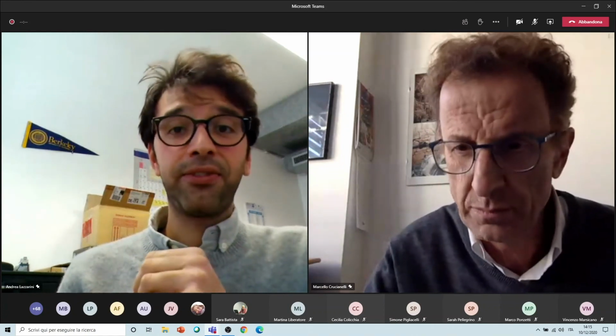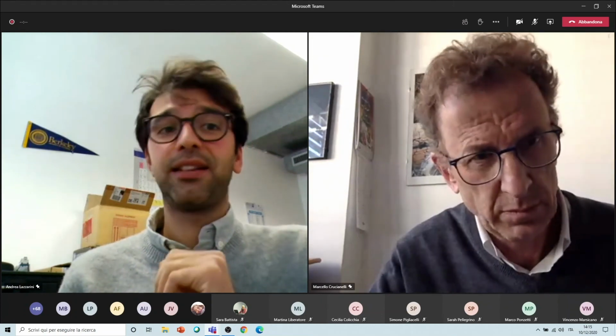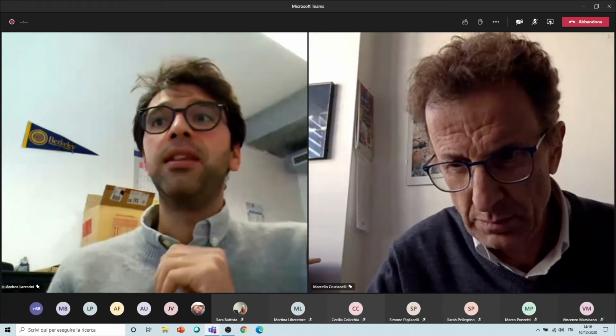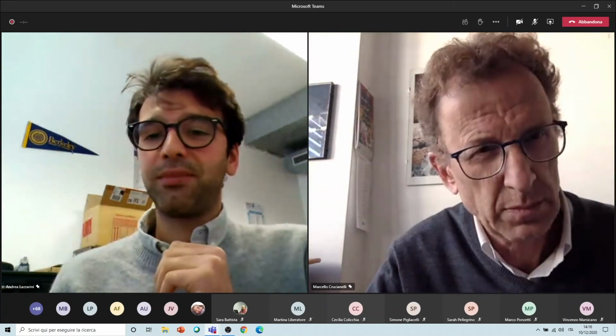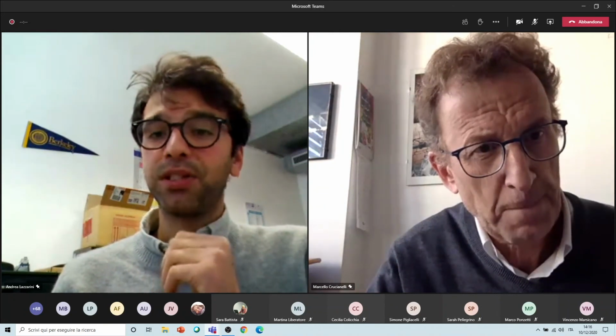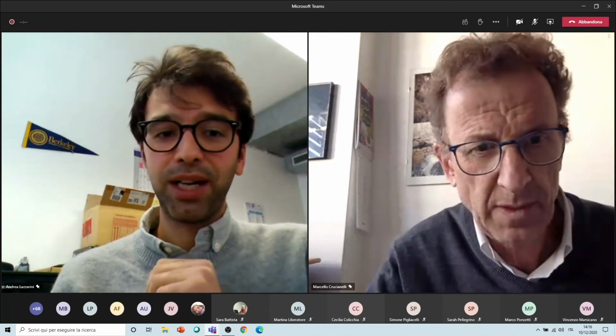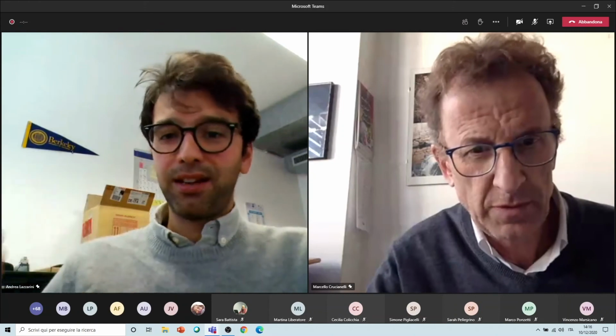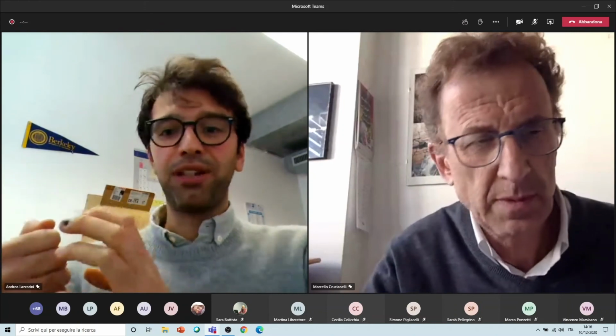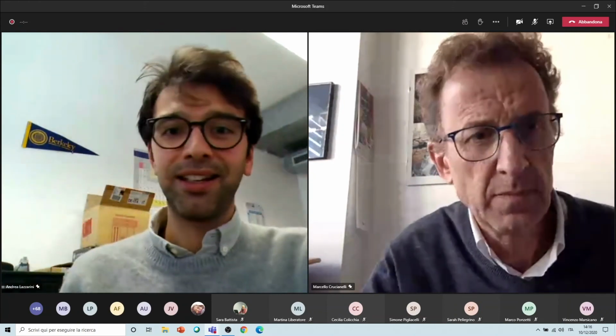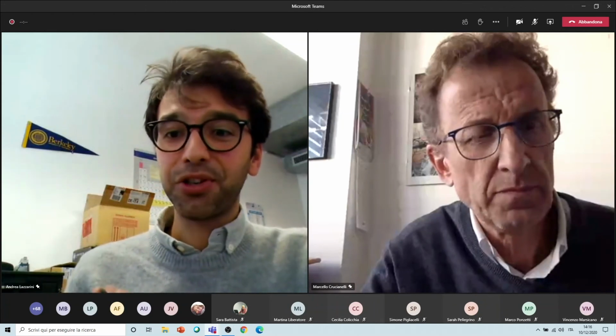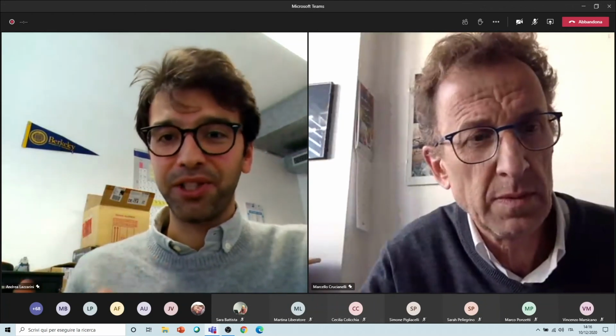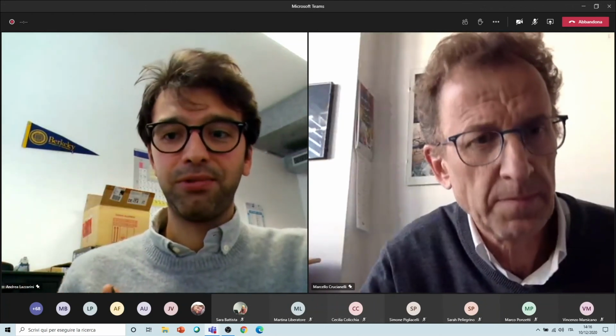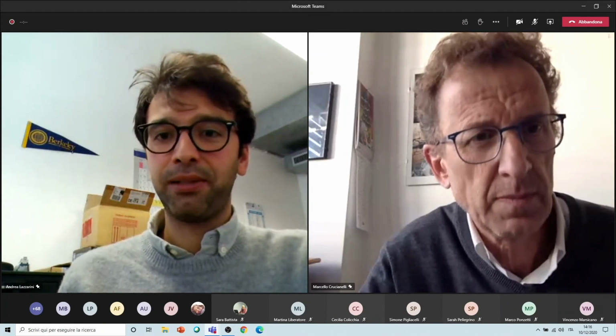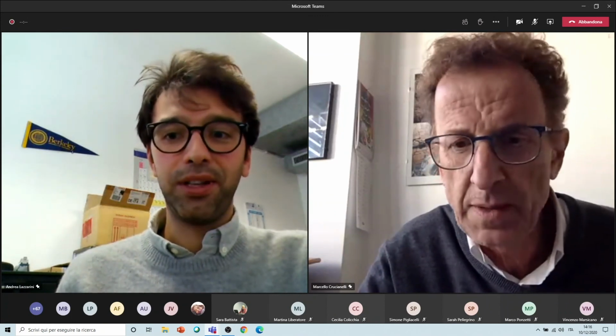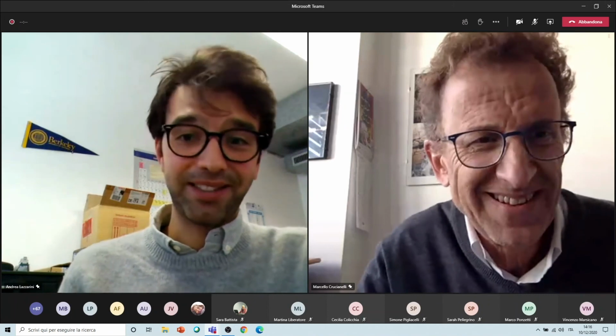And again, for liquid phase catalysis, leaching, sometimes it can be dramatic also, because if you don't keep it into account, you might think, okay, I'm recovering my catalyst, but then you don't have any more active phase that remained in the reaction environment, so you are not aware of this problem, and you have to be careful on this as well. So it's true, these are the two main drawbacks.